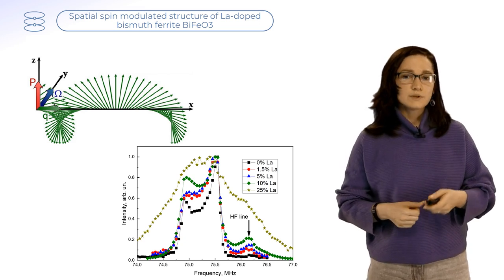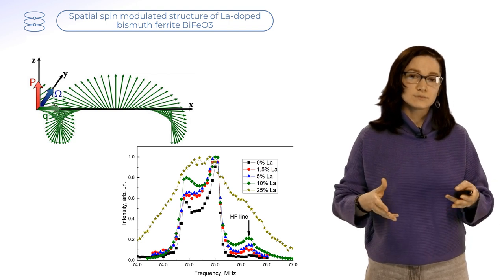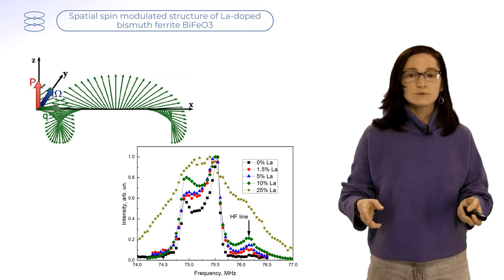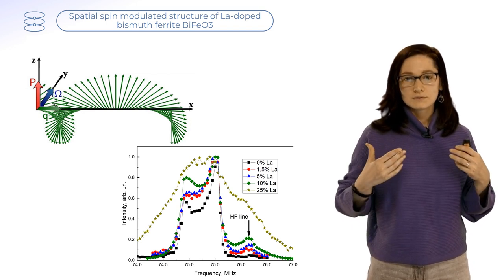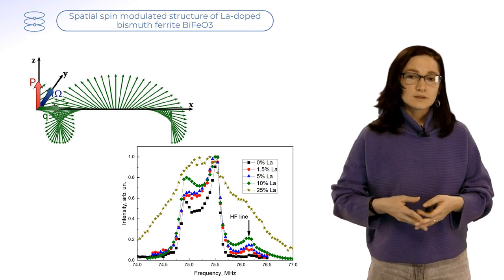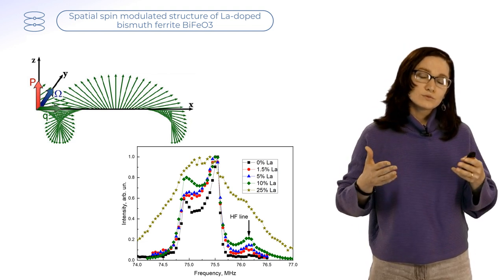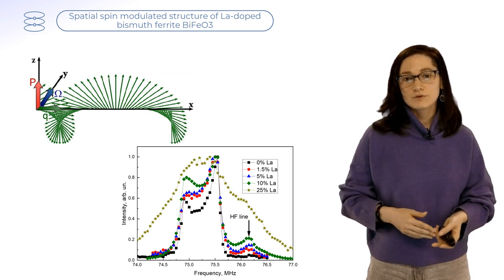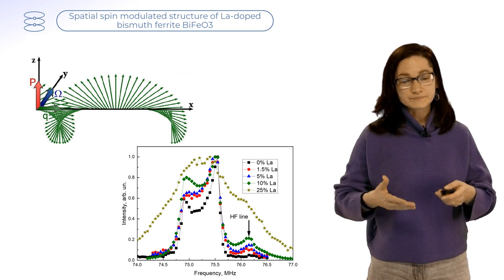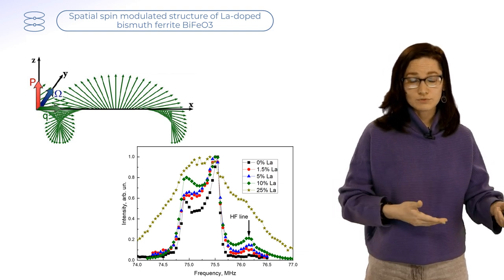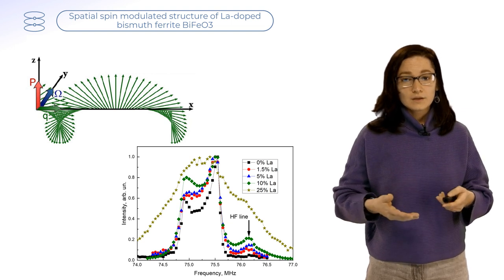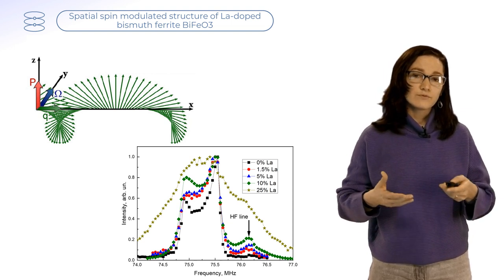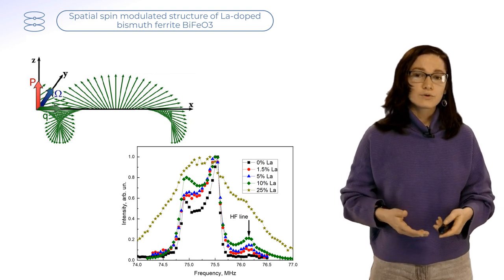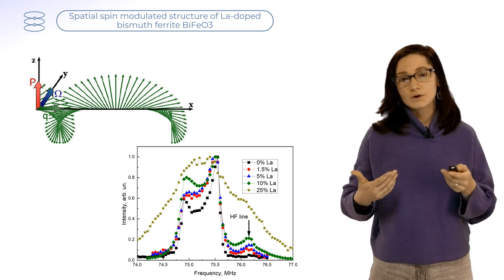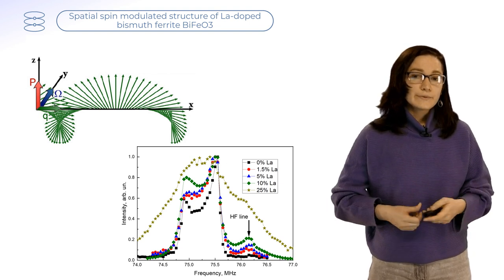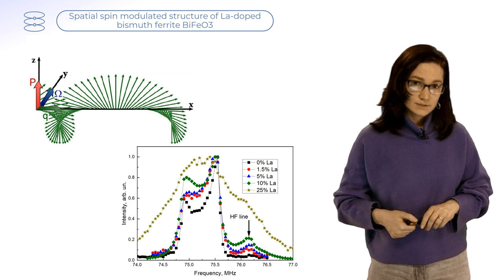As I have already said, doping is one of the ways to influence this magnetic structure. It can be modified, it can be suppressed, it can be strengthened. So we conducted a series of studies to see how doping by lanthanum, terbium, or strontium influences the magnetic structure and magnetic properties of bismuth ferrite. Here you can see the spectra obtained for lanthanum-doped bismuth ferrite for the level of doping in the range from 0 to 25%. Here you can see that NMR spectroscopy is a very sensitive method.